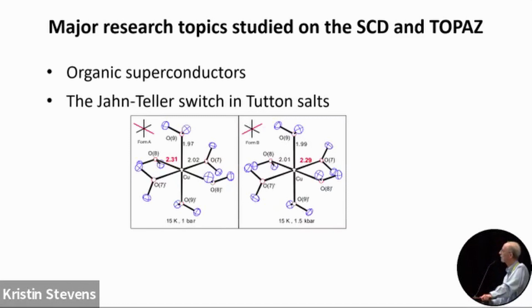The Jahn-Teller switch and Tutton salts. Charlie Simmons came to do an experiment, and he wanted to test to see what happens with the Jahn-Teller distortion in this hexa-aqua-copper complex, they're called Tutton salts. And we knew that there was a difference between hydrogen and deuterium. And when he applied pressure to the deuterated salt, it actually switched. And so now it's isostructural with the hydrogen.